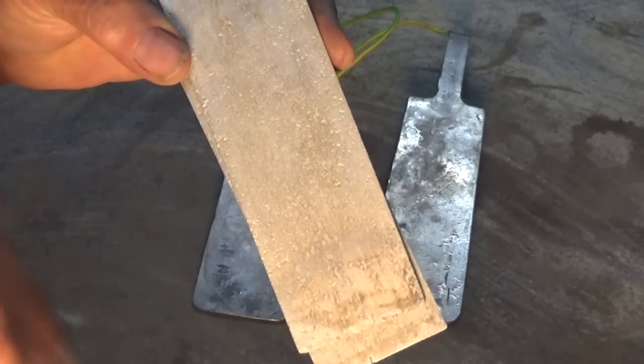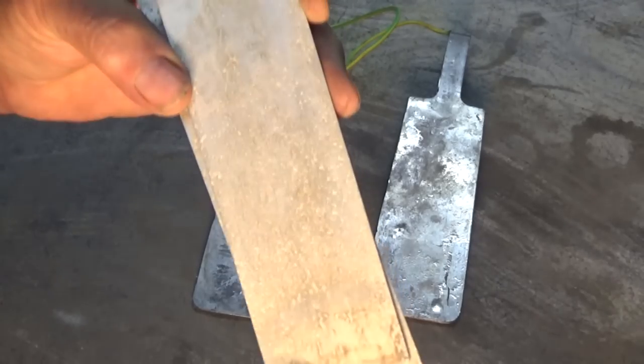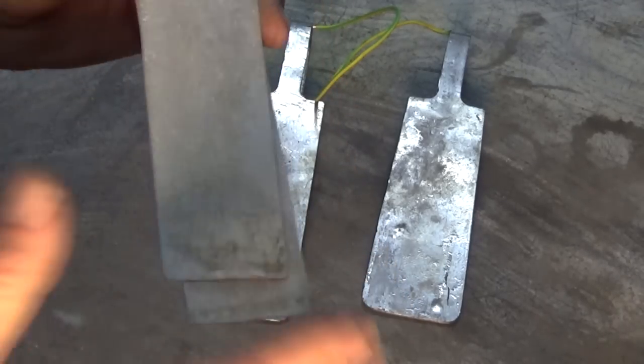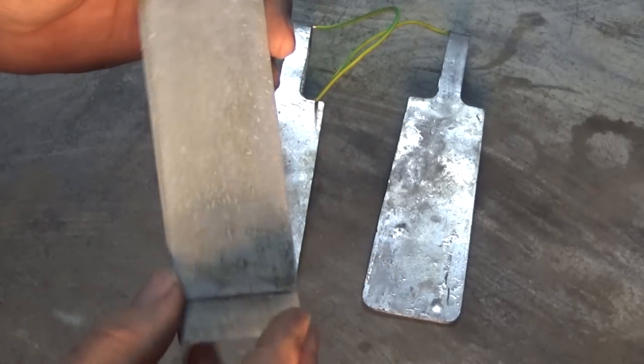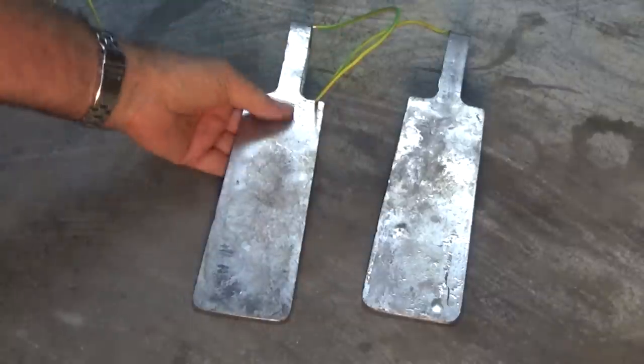At one point I was just leaving the cathodes in the tank and it might be six months before I come back and used it. I found that one set of cathodes had been completely dissolved, nothing left of them, and all of that aluminium that was dissolved ends up in the electrolyte. That can upset the balance of the electrolyte.